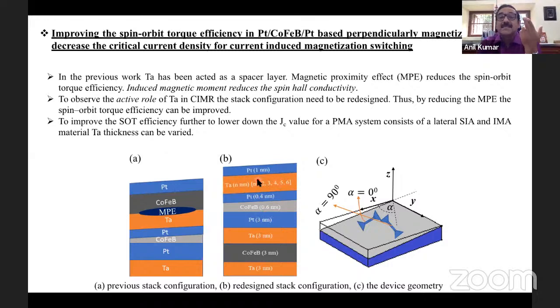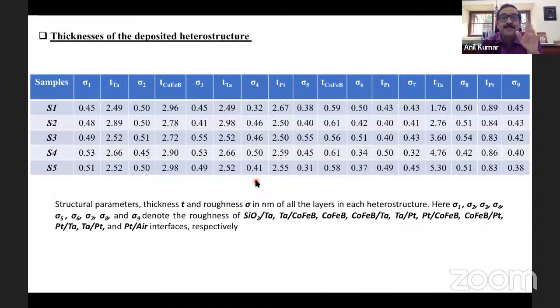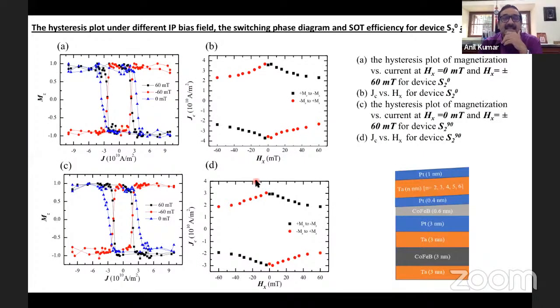But when we put tantalum directly on CoFeB, that destroys the CoFeB. So we just put a very, very thin, discontinuous layer of platinum, and still this tantalum is not destroying the cobalt and boron, and at the same time, it gives the negative spin Hall angle. So that is the aim. Again, we do all this X-ray reflectivity and understand everything.